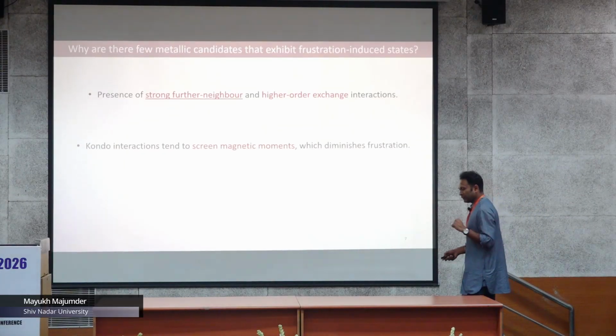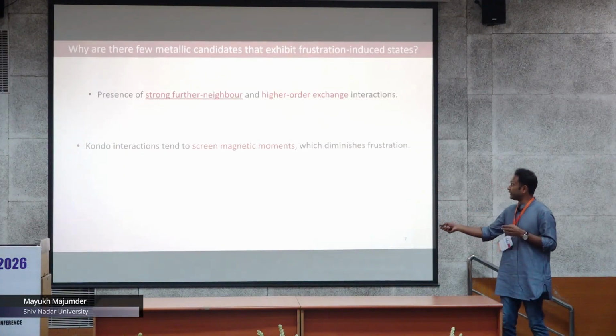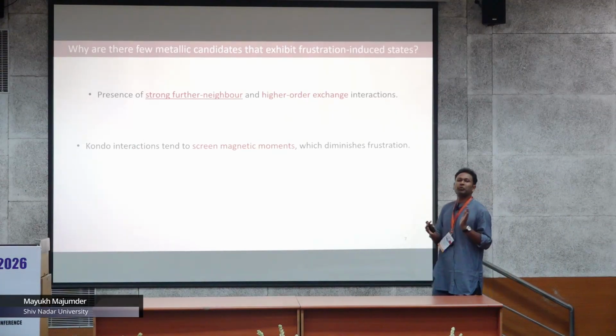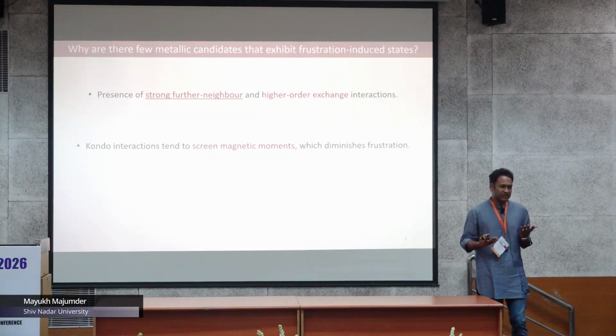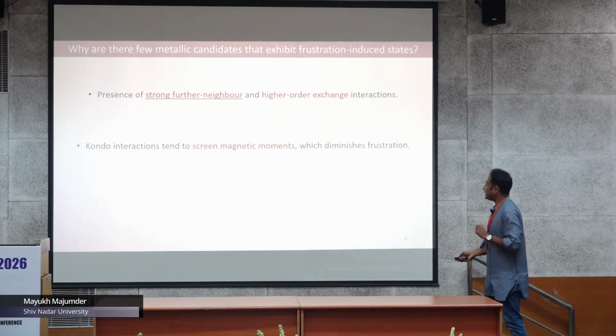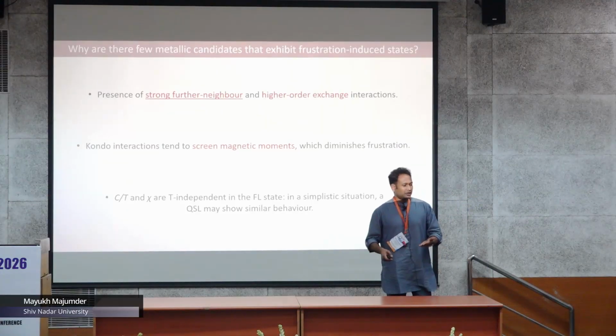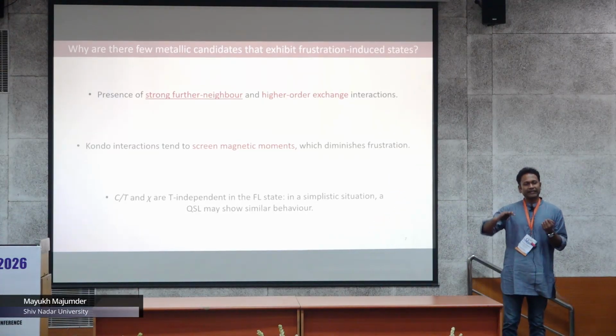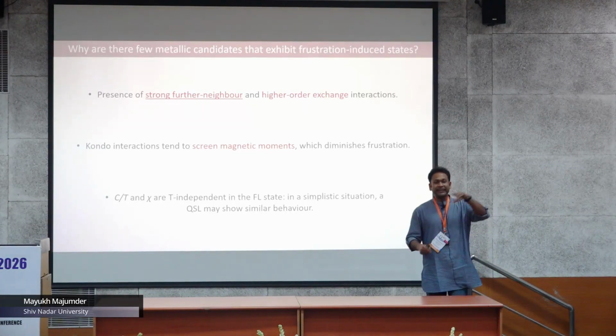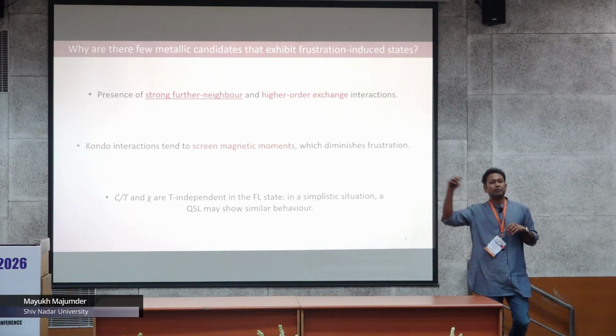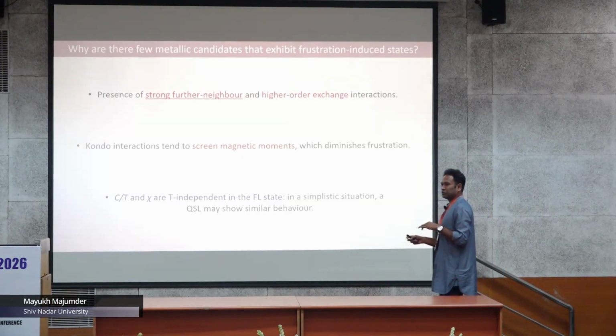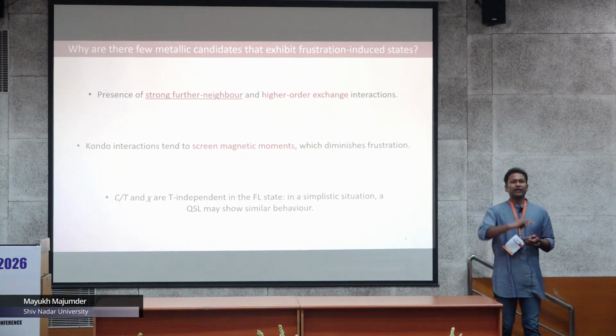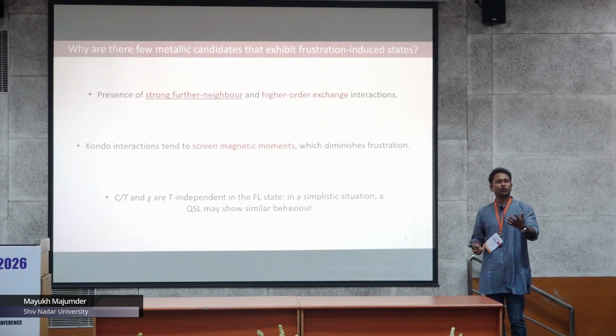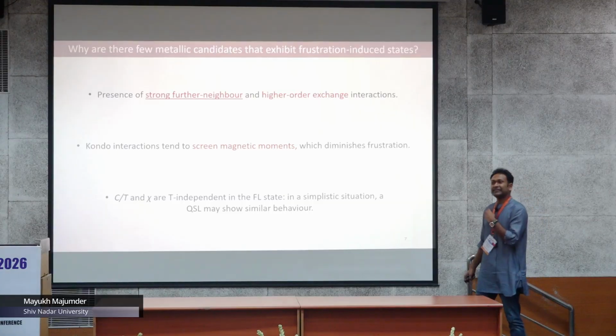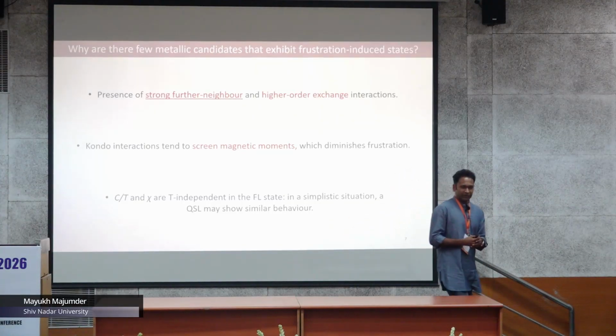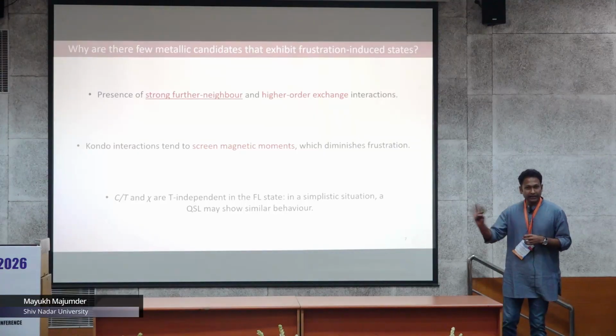Another point, as already mentioned, is that in the high J limit, you have a dominating Kondo interaction that often screens the magnetic moment completely. And if so, there is no chance of having any frustration, because you need a finite magnetic moment there, right? And also, if you are thinking about probing the quantum spin liquid state in metals, as you know, in the Fermi liquid state one would usually expect the heat capacity over temperature or the susceptibility to be temperature independent, right? And in the case of a quantum spin liquid, in a simplistic scenario, if you have a spinon Fermi surface, that should also give rise to a similar kind of temperature dependence. So it is relatively trickier to figure out from bulk measurements whether you really have a quantum spin liquid or not in the case of metals.